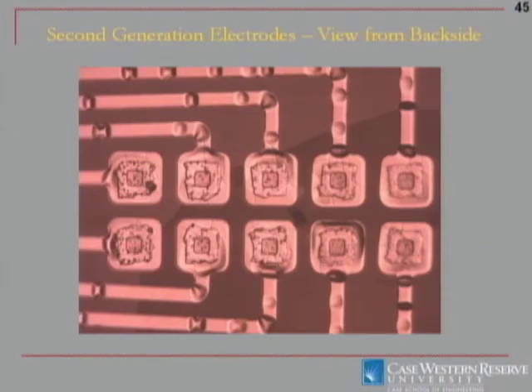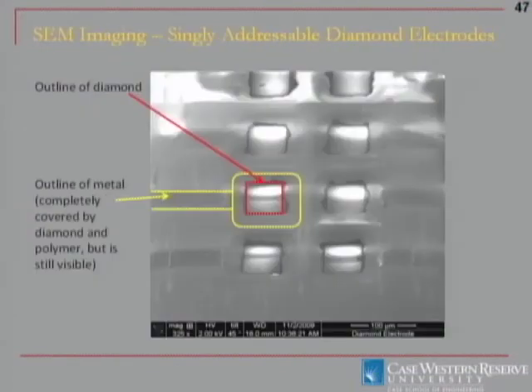The diamond is optically transparent, and so is the polymer. So what you're seeing here is all the layers through at one time, even though the diamond is the only thing that's exposed on the electrode side, and nothing is exposed on the back except the polymer. That's kind of shown here. So here's the diamond side, and you can see here's the diamond popping up out of the polymer. And what's cool about this is that we flip the diamond over during this process, so now the diamond surface is very smooth, reflecting that original surface where it grew on the silicon dioxide. And you can sort of see where the electrode contact is underneath the polymer there.